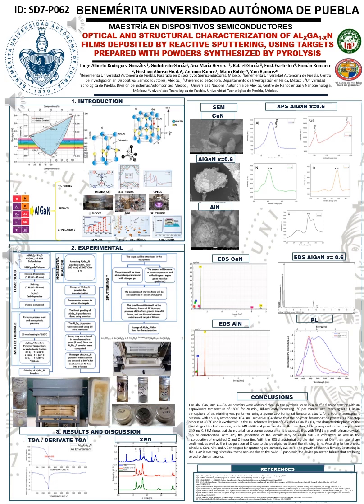With XPS, the generation of the ternary alloy of AlGaN, X equals 0.6, is confirmed, as well as the incorporation of unwanted oxygen and carbon impurities. With the EDS characterization, the high levels of oxygen in the material are confirmed, as well as the incorporation of carbon due to the pyrolysis route and the nitriding time. According to the project schedule, GaN, AlN, and AlGaN targets for sputtering are currently available. The growth of the thin films by sputtering at the BUAP is on hold, since due to the non-use during the COVID-19 pandemic, the device presented failures that are being solved with maintenance. Thanks.